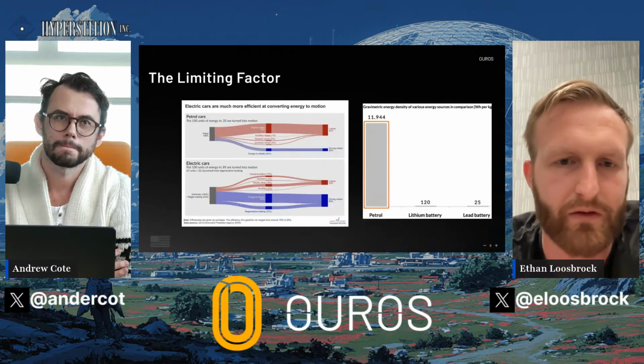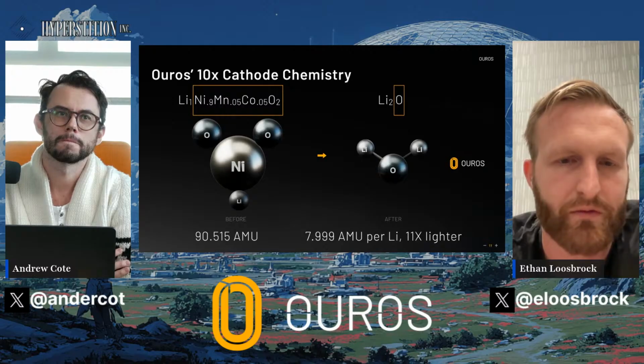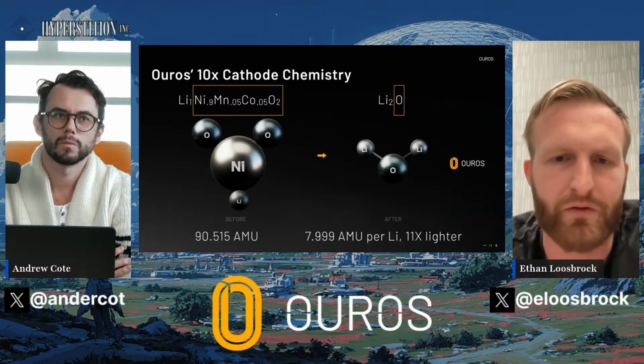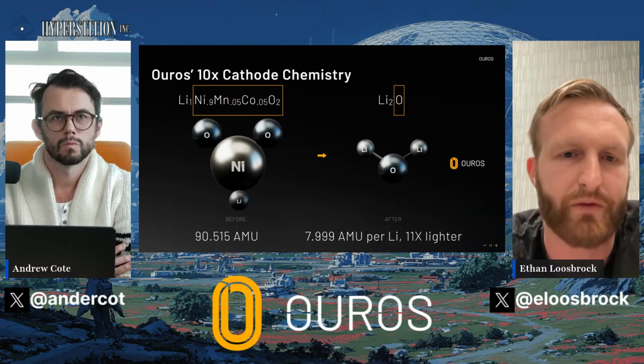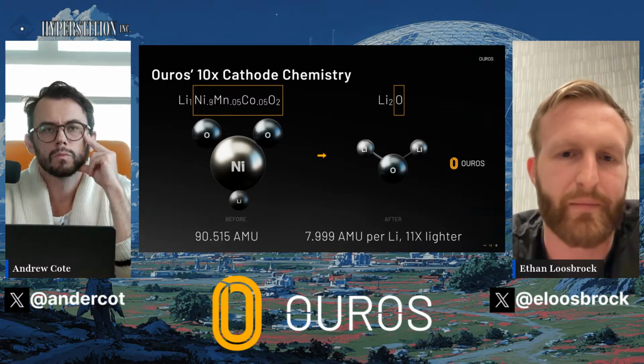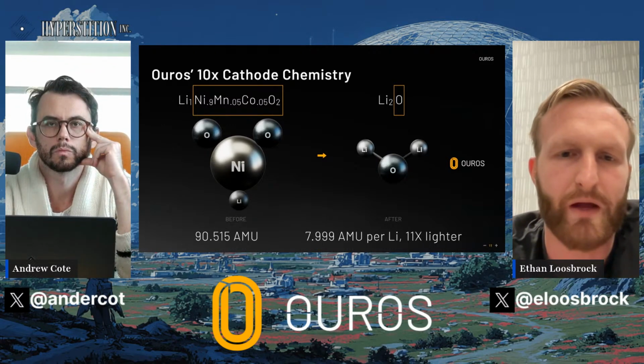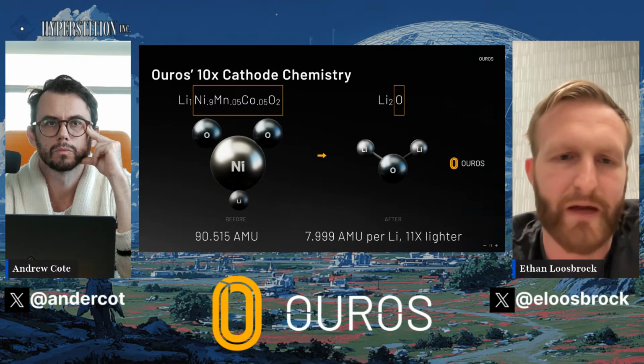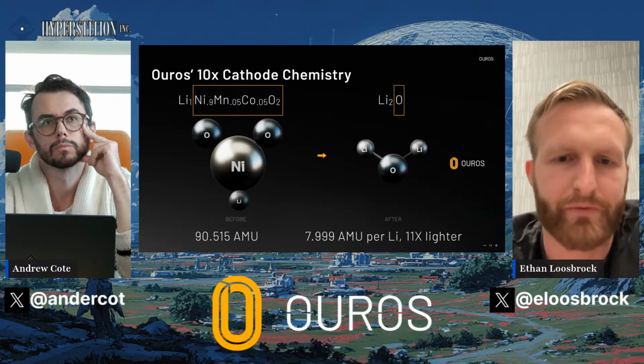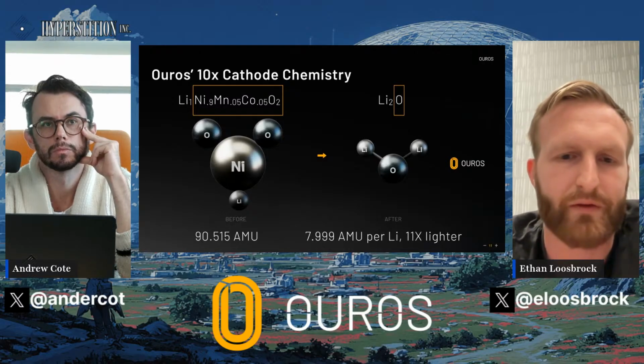Yes. Okay. So our angle is primarily a new cathode material. Instead of NMC, we are using lithium oxide. So you get two benefits here. One is that oxygen is much lighter than nickel manganese cobalt oxide. And the second benefit is you get two lithiums on one oxygen instead of one lithium per nickel oxide. So mass-wise, you're looking at about 11 times lighter on the cathode level.